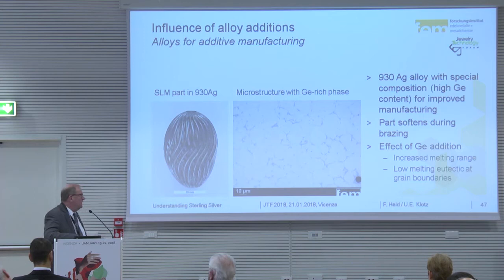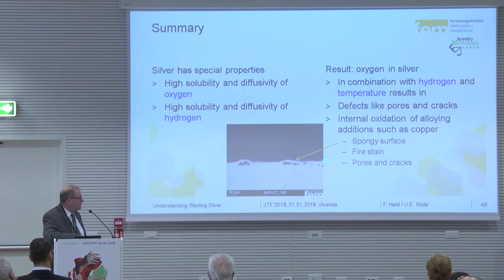What you see here is the surface of a sheet of metal. There was copper oxide in it under the surface. We make annealing with hydrogen, and you get a water steam reaction here, and it looks like a mushroom surface.